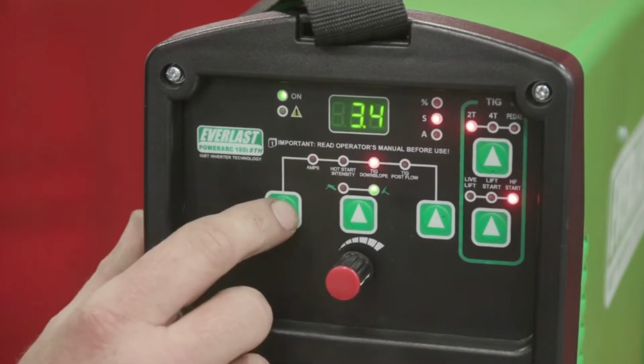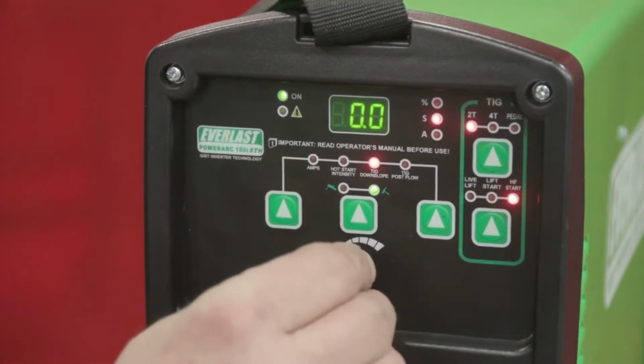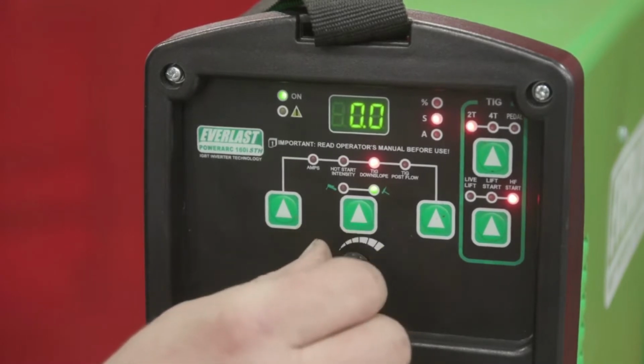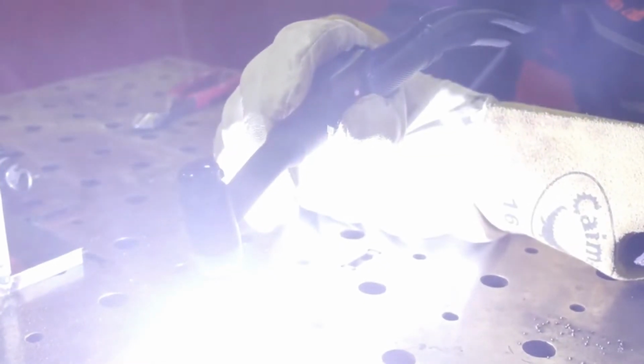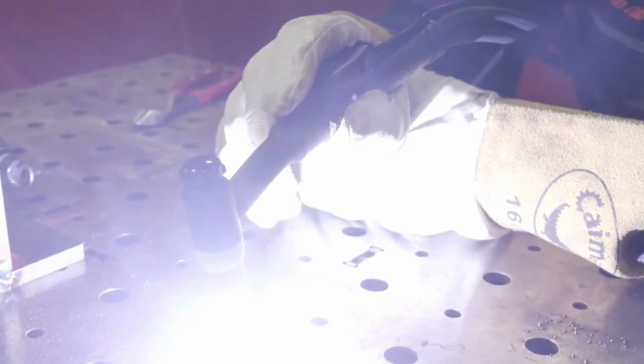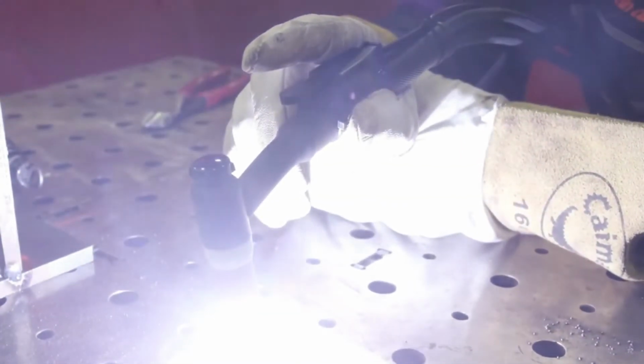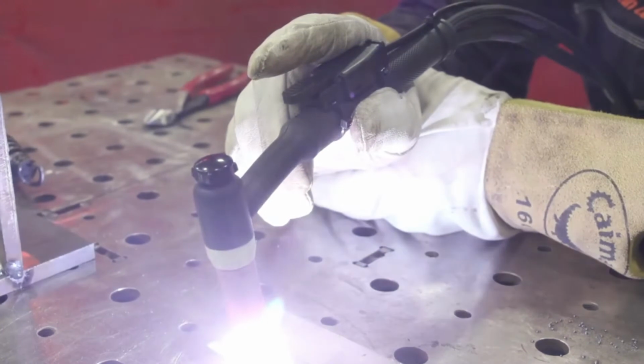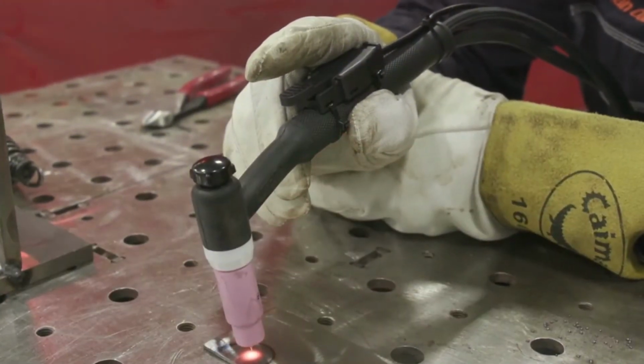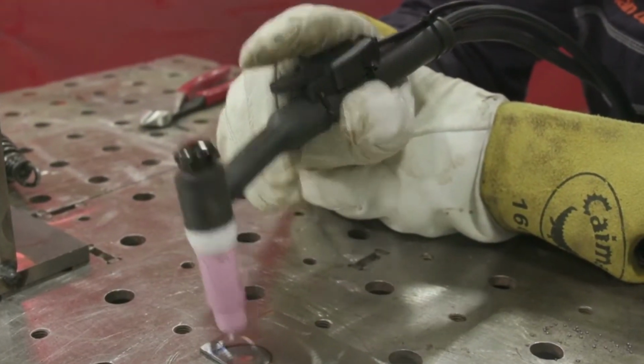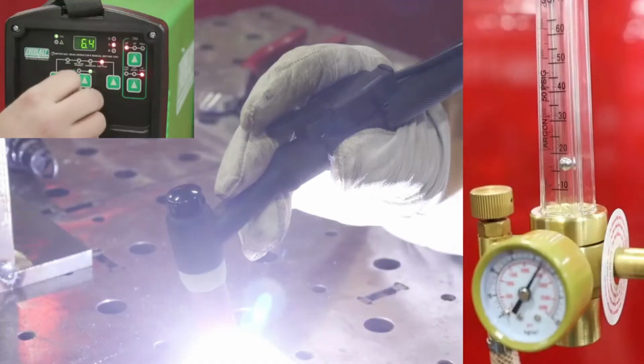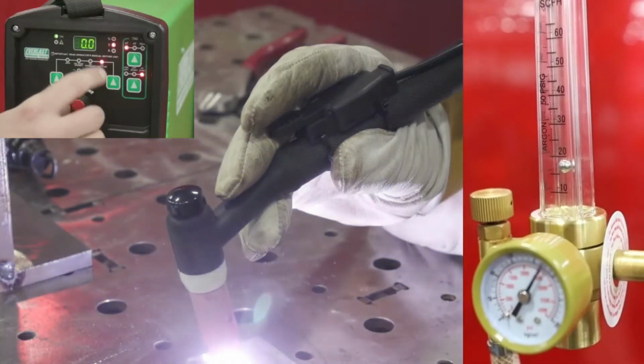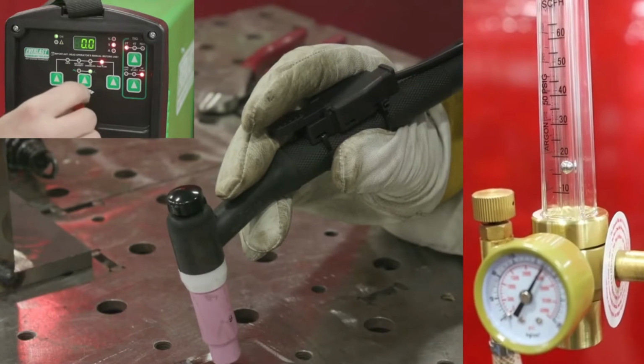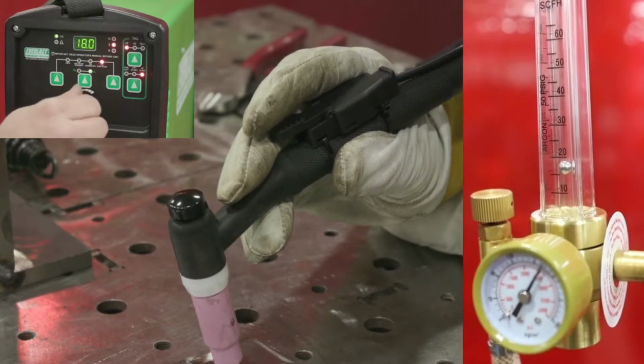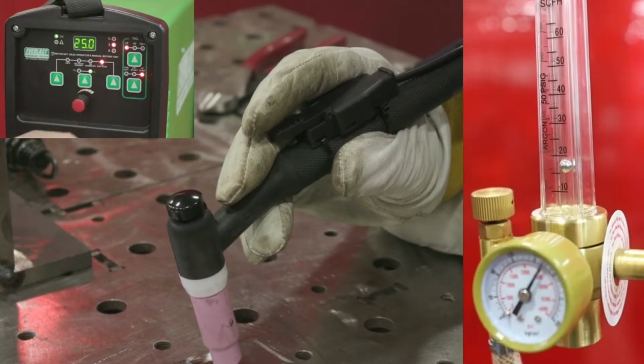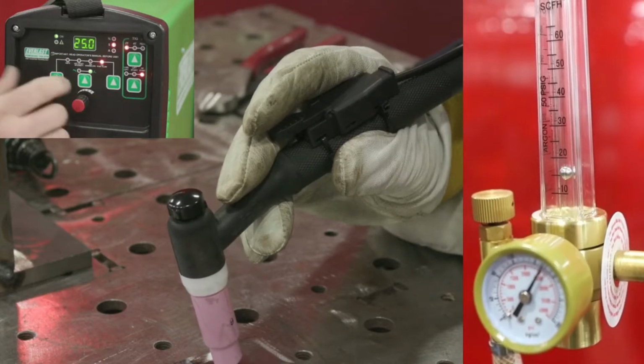All right, so our next one is downslope. It basically acts like a foot pedal. You set the time in seconds to taper off your amps. When you hit the remote or pedal to kill the arc, it will taper down from 100 amps all the way down to 0 without leaving a crater there. You can go from 0 all the way up to 10 seconds. So post flow is the next one. You set the post flow in seconds. This machine goes from 0 to 25 seconds. If you set it for 5 seconds, your argon will remain on for 5 seconds after you stop welding.